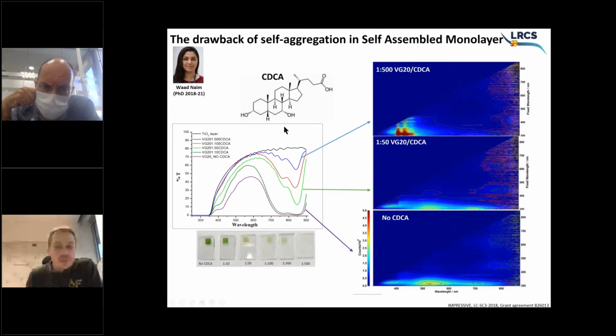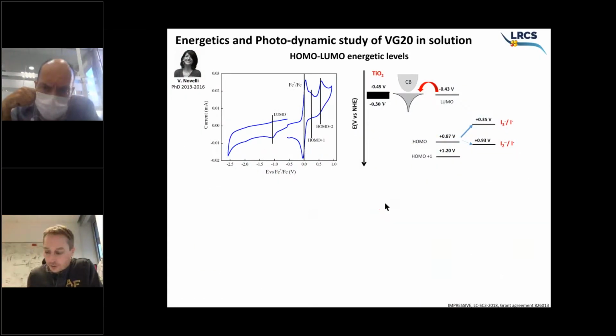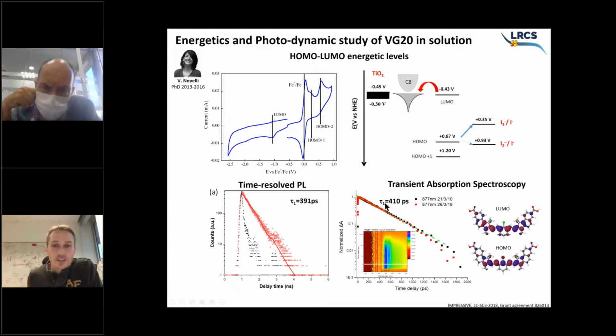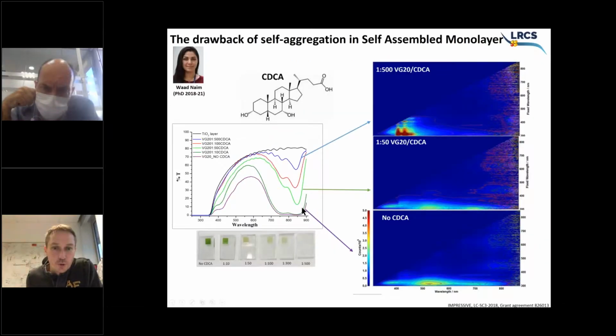So if you sensitize the nanocrystals without the deaggregating agent, this is what it will turn out. You will not only have this very nice solution shape of the dye, but you will have a very broad absorption band with contribution also from the near infrared. So we have some J aggregates here, but very strong contributions of H aggregation, which makes the coloration of the devices really green. So it's not green because of the monomer, it's green because of the H aggregates that are formed as a self-assembled monolayer.